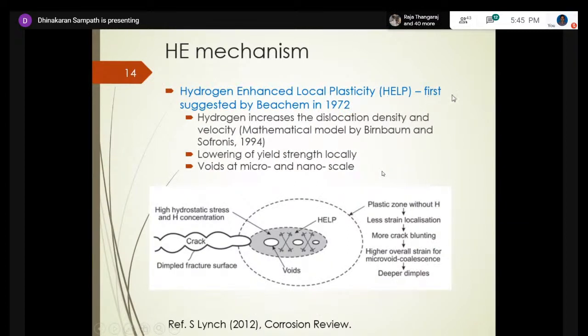Hydrogen enhanced local plasticity is a very recent one, but it is a very comprehensive mechanism, which tries to explain several of the observed phenomena in this failure. What it says is, in the presence of hydrogen, dislocation density increases and velocity also increases. So what is a dislocation? It's a line defect, which is actually the basic unit of plasticity. That means it will create permanent strain in the lattice. Several of these happen, and that is when we see yielding and further hardening, depending on the material type.